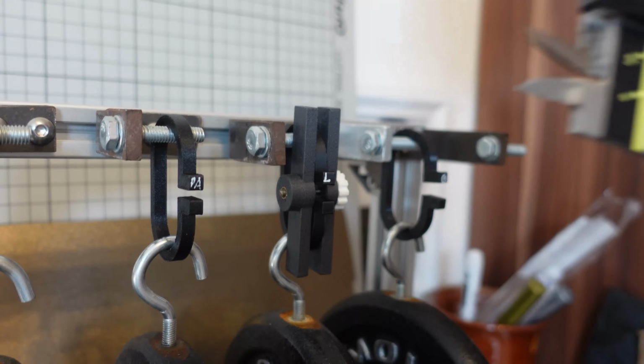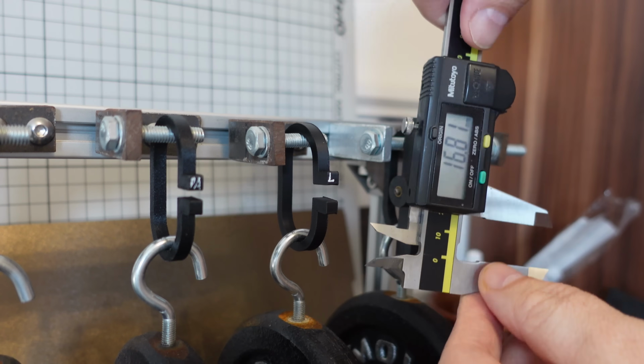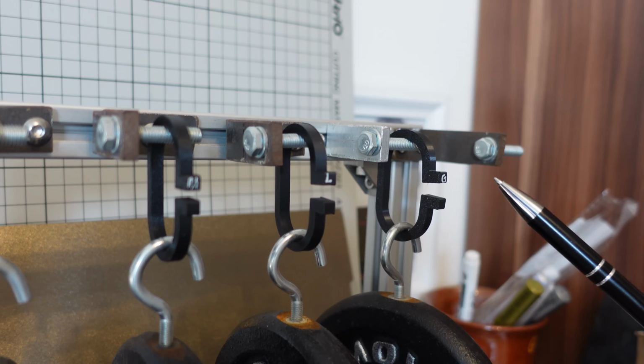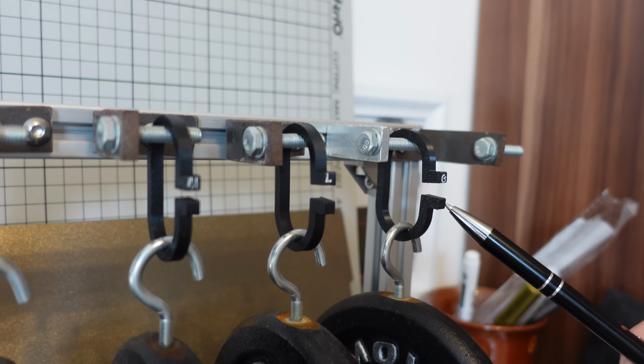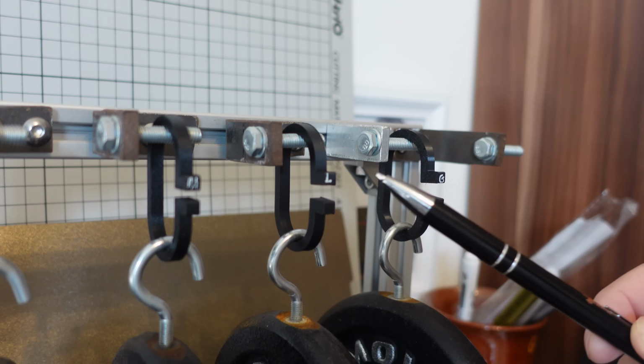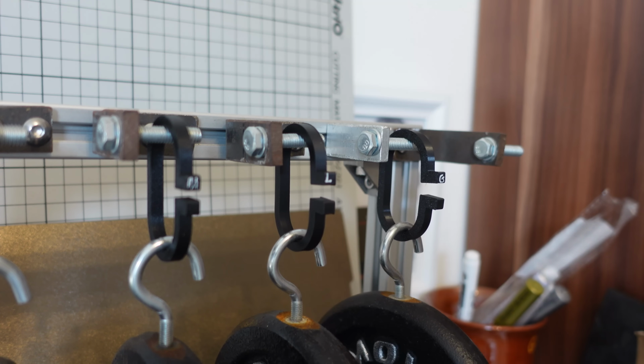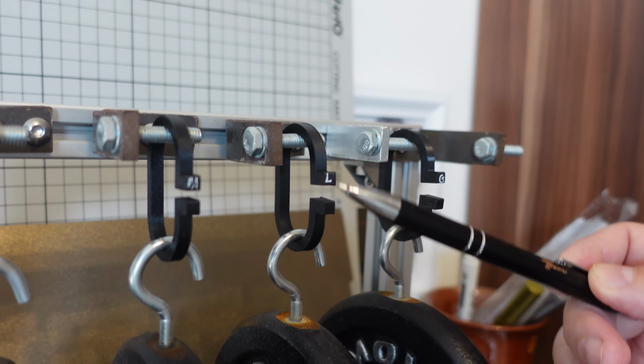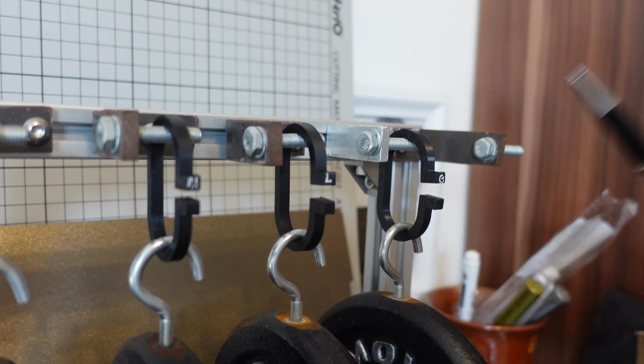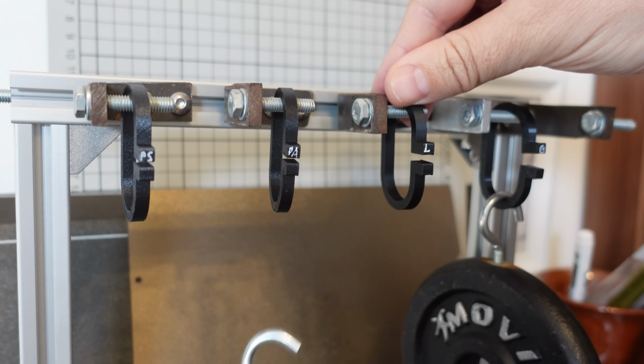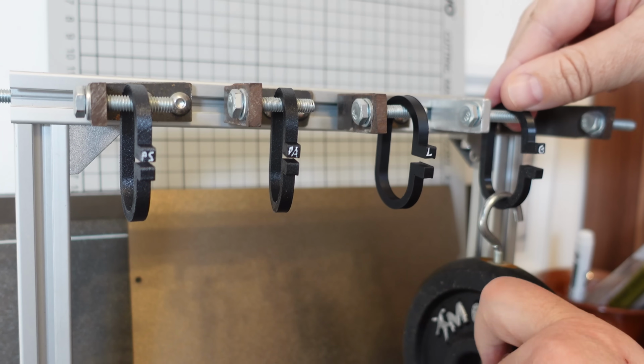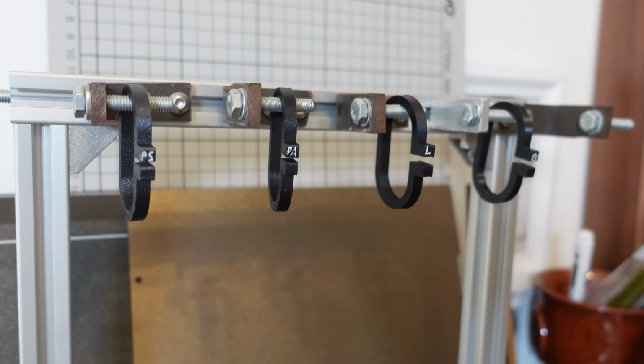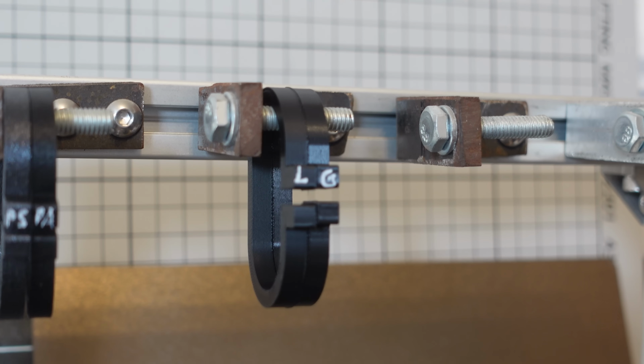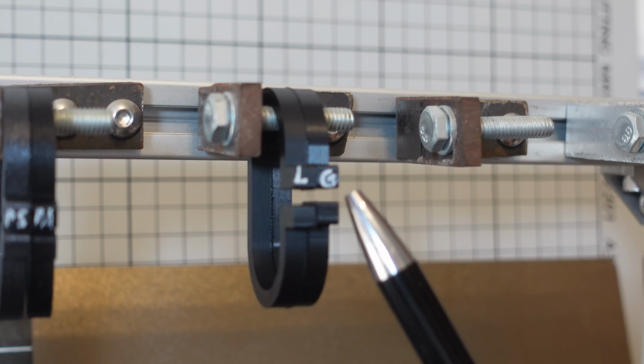16.15, 16.81. Looks like this PETG almost completely stopped with the creeping. Still has bigger deformation than the PLA, but if I would continue this test maybe one more week, I'm quite sure that here on the PLA the deformation would be bigger compared to the PETG. I'm not sure is it visible on the screen too, but definitely I can see more permanent deformation on the PLA compared to the PETG.